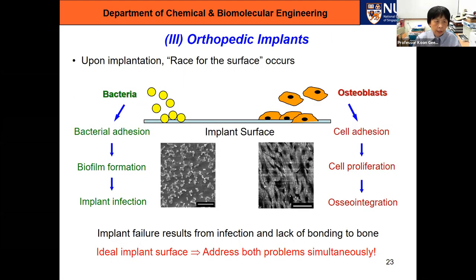Let me now move on to the third area of applications. This is orthopedic implants. So when such implants are placed in the body, the race for its surface occurs. And this race is between bacteria and bone cells. So we can imagine, if bacteria wins this race, what happens? If bacteria wins the race, they will colonize the surface, form a biofilm, and increase the risk of infection, because the osteoblast will not be able to displace the bacteria that's already on the surface.